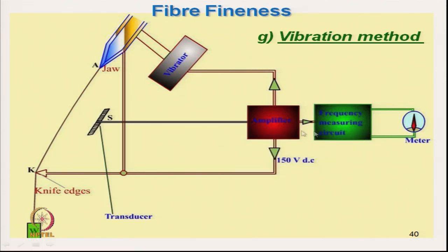Now, this is the technique. Here the vibrator is there, and the fiber is vibrated with a wide range of frequencies, and where the maximum amplitude occurs, that frequency value is taken.